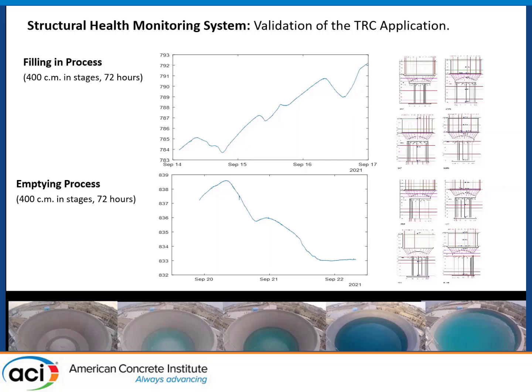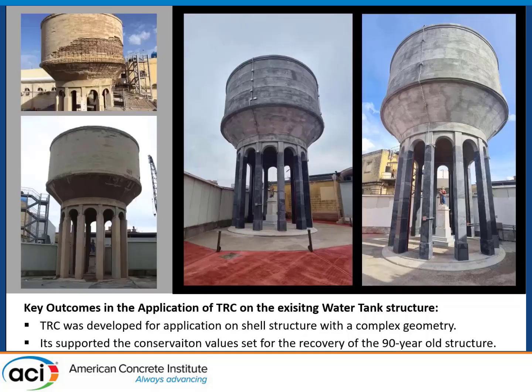And we integrated many sensors in the structure. We have full sensing, with strain gauges, to see exactly what's happening within the original structure, which was repaired and restored, of course, and also the textile reinforced mortar application on the surface and at the interface. One defect we experienced, for example, in real application was some gaps which we had to fill in with epoxy injection. We identified these through ultrasonic and acoustic emission techniques. So that is another realistic scenario we have to deal with, which we are also studying. But the end result could be validated. So we validated the structure.